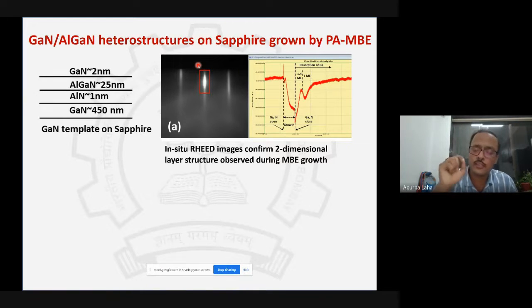So that is why we need to look at the very early stage of growth, what is happening on the surface. As I said, the streaky RHEED pattern is a signature of 2D layer formation, and that immediately tells us, okay, we are in the right process conditions that help us grow the two-dimensional layer. Apart from that, what is very important is that it is not a mixture of two materials. As sources, we use gallium and nitrogen plasma, for example. Now, this nitrogen and gallium are coming onto the substrate at the same time, and there are reactions happening to form the crystal.